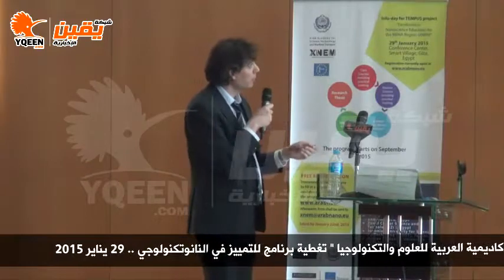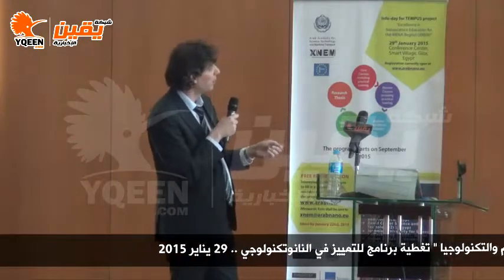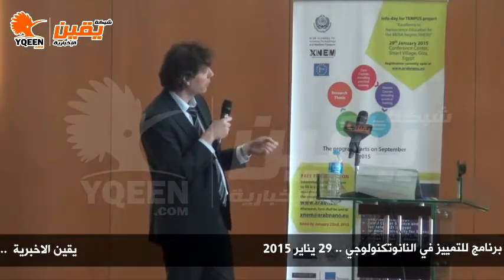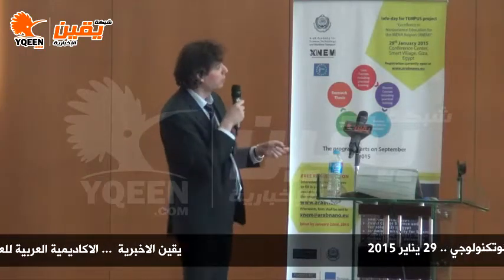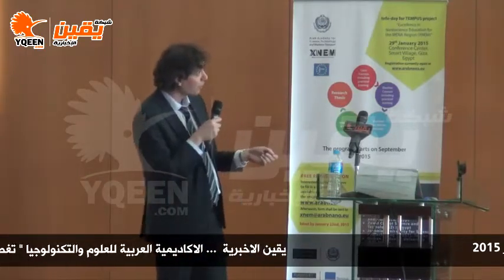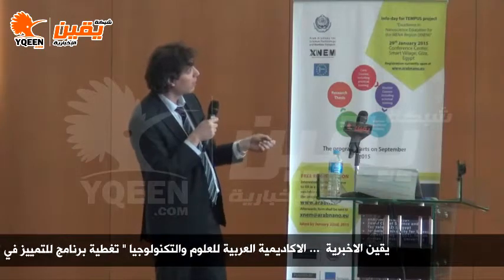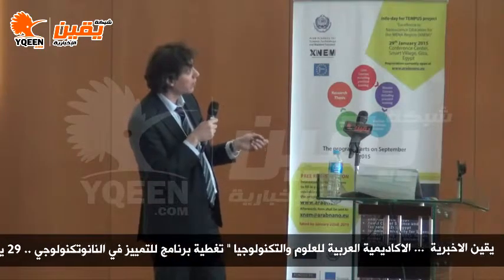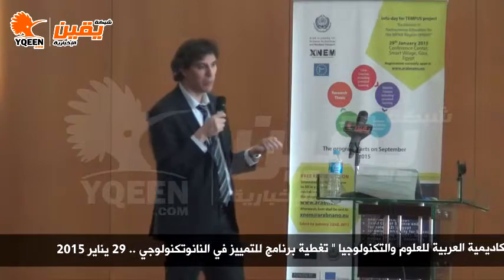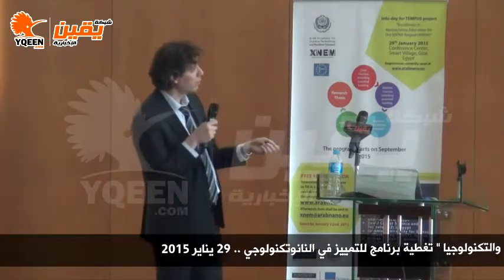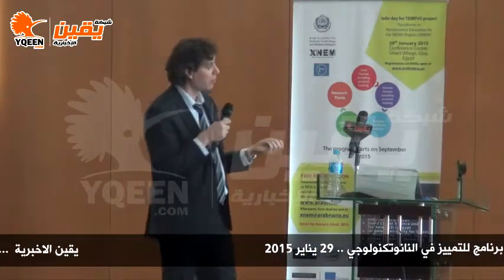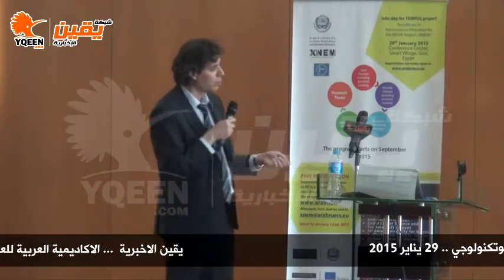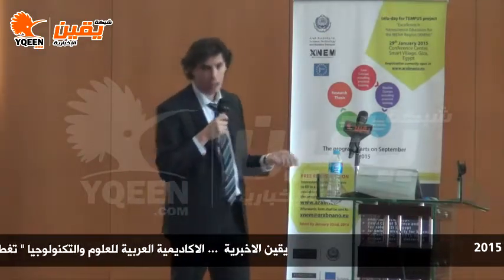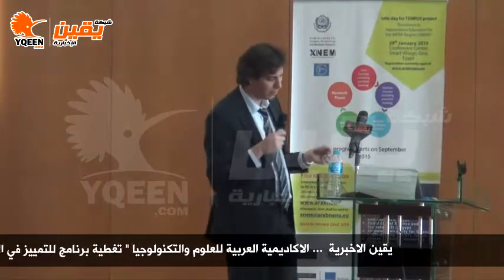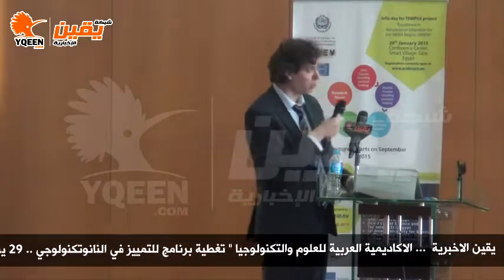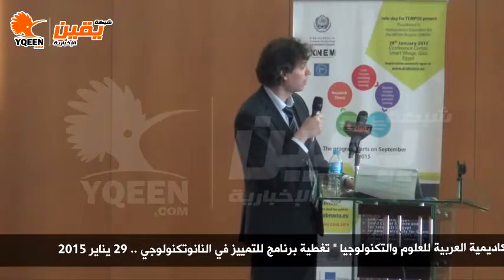The energy band diagram, you can see that if you stick, so here I'm trying to make a heterojunction. If you stick the diamond to amorphous silicon with a gap of 1.7, you have a large conduction band offset, and that means that you only have a unipolar device. Only holes can travel across the junction, but not electrons. So it's good in a sense that it makes hole conduction and therefore fast switching devices. But on the other hand, you still cannot make a PN heterojunction based on diamond.